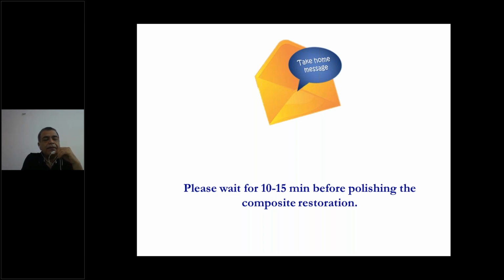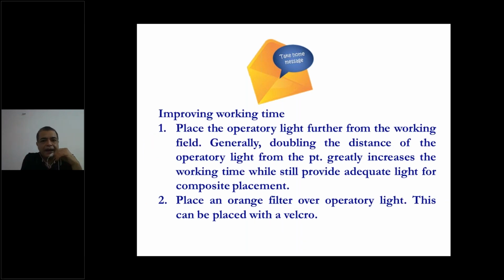If you start polishing your composite immediately, you have not allowed it to complete its polymerization totally, thereby reducing the strength of the composite, or reducing the total longevity of the composite restoration. So I always recommend waiting for 10 to 15 minutes. Please also note that your operatory light can also cure composite, because it has visible light as well as UV light and infrared light. This can also cure composite, but bad curing will happen. So I personally advise you can either use an orange filter over the operatory light, or just keep it at least at double distance. It gives you sufficient time to work on the patient, and the curing does not happen.